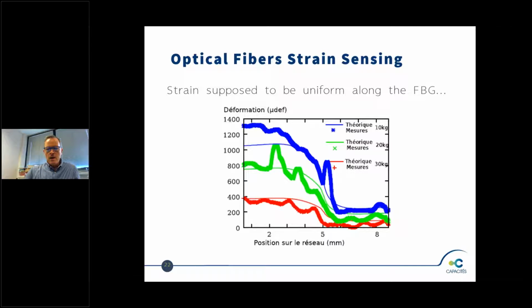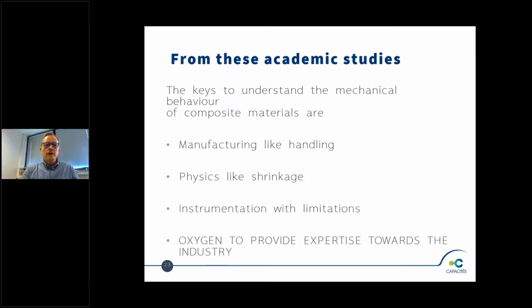And it means that people who measure with fiber Bragg gratings inside technical textile preform should pay attention to the validity of their measurements. Otherwise, they will just say something wrong. And we proved in the PhD of Pierre-Antoine Morvan that the error could be up to 30%. So it's not satisfactory, let's say, to use this instrumentation technique to assess strain field in materials like this one. Okay, so from these academic studies, the key is to understand the mechanical behavior of composite materials or the manufacturing, like handling.